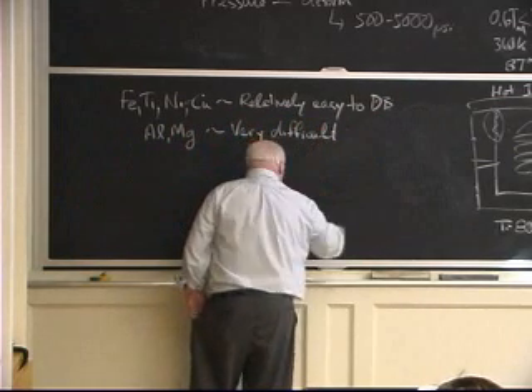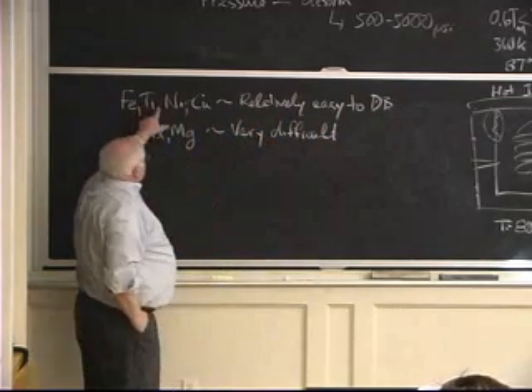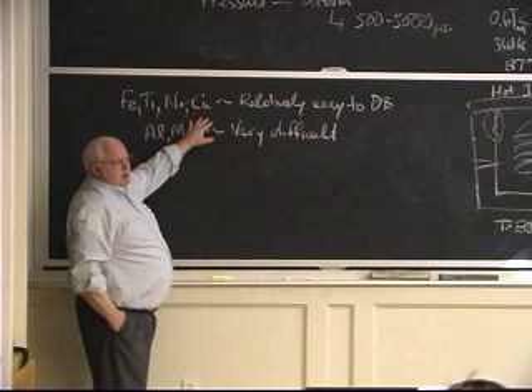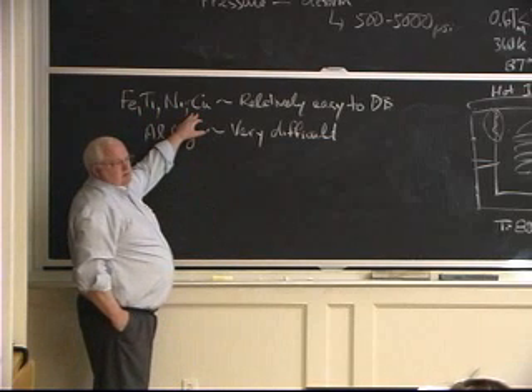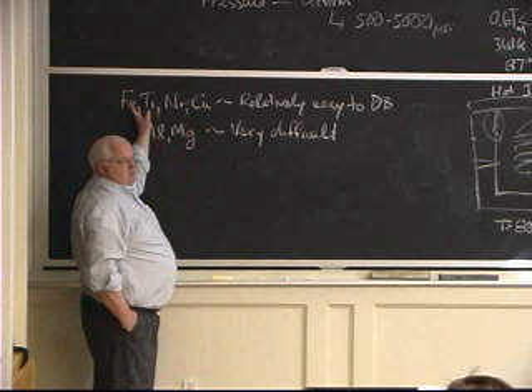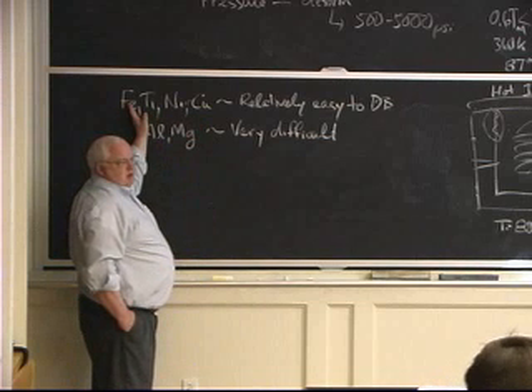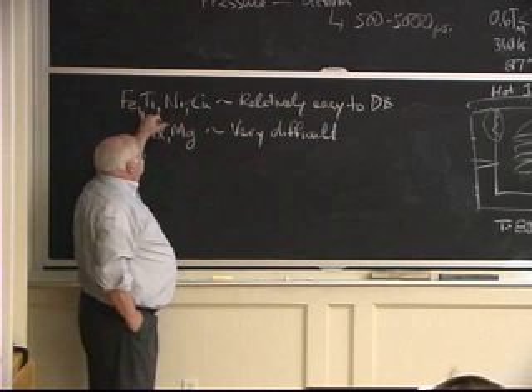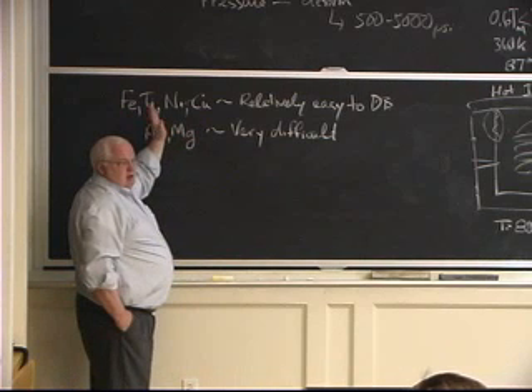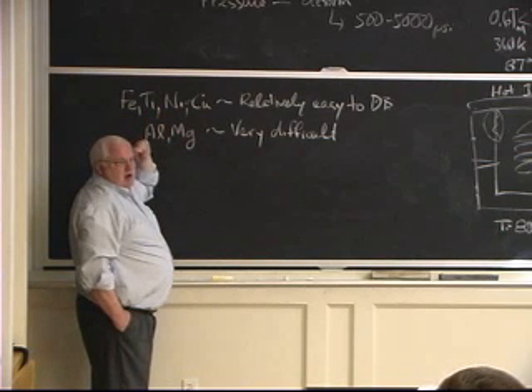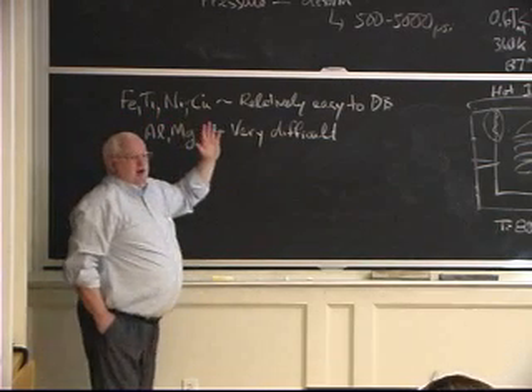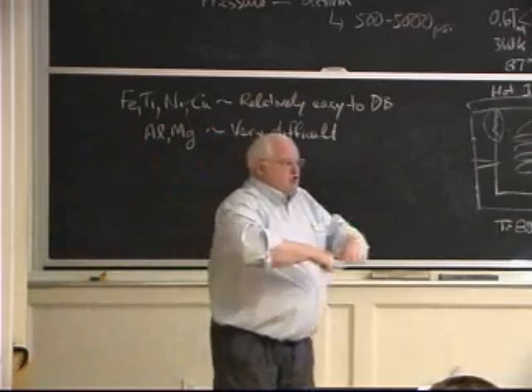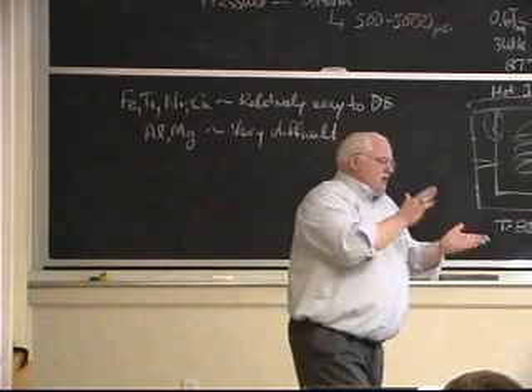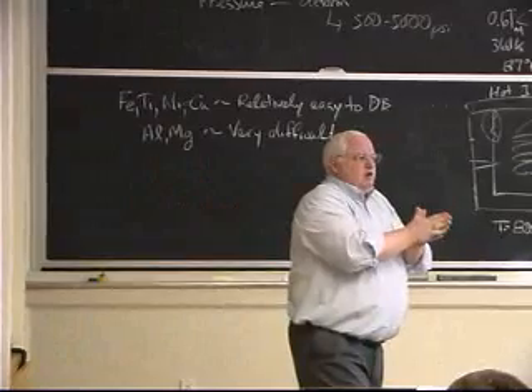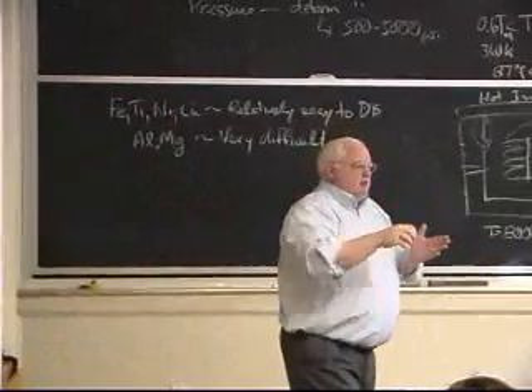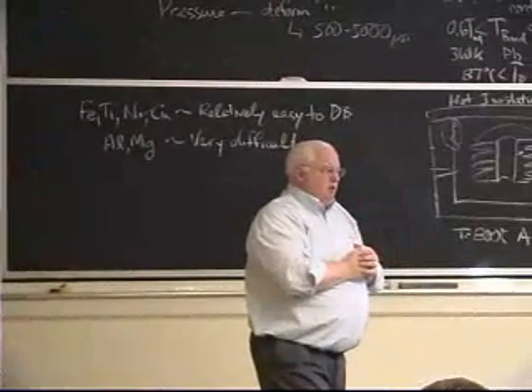The reason is iron, titanium, nickel, and copper will dissolve their own oxides. Iron will dissolve oxygen. So if I have an iron oxygen surface contaminant, the oxygen can just diffuse away into the iron, and the contamination doesn't have to be extruded out of the joint. In cold welding, I have to extrude the contamination out of the joint. If I do ultrasonic, I'm just kind of moving it aside, and I'm burying little islands of contamination. I never get a perfect joint.